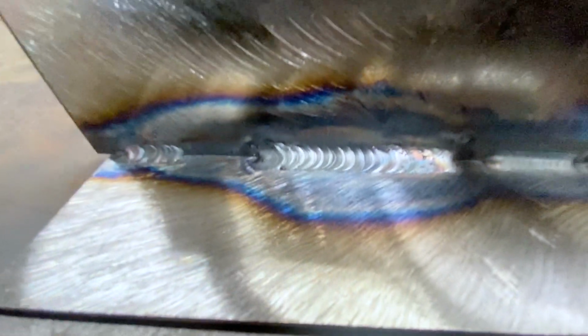And here we have when my puddle was too hot. When I was running too much amperage, you can see it's starting to pull some silica and mill scale into the weld and fighting undercut, and I was having to move at a faster pace because my puddle was too hot. You can see the undercut on the top side there.